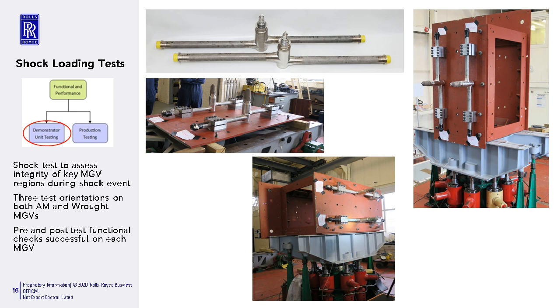What we found was that all valves successfully passed the pre and post functional checks. No deterioration of valve function in terms of seat leakage. And we also closely examined the valve stubs, looking for any signs of distortion or cracking, and none were apparent.